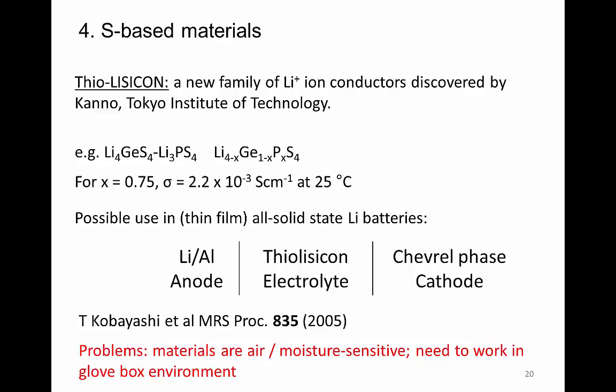It's not as high as is theoretically possible. So a strong liquid electrolyte may be 10 to the minus 1 reciprocal ohm centimeters, but nevertheless this is a very high conductivity. And so such materials are being considered for thin film all solid state batteries with, for example, a lithium aluminium alloy as the anode, Thio-LISICON electrolyte, and then a sulfur based cathode material. A Chevrel phase is a complex sulfide rather than an oxide. So there's certainly developmental work going on, especially in Japan, on sulfur-based materials.